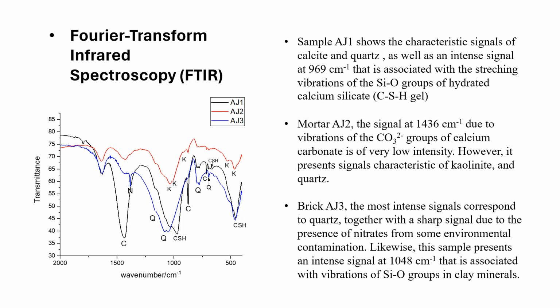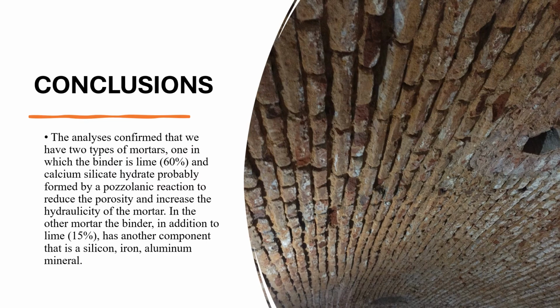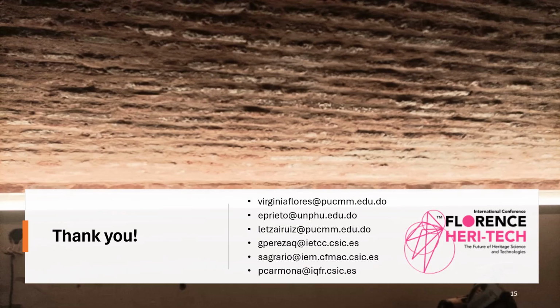We can conclude that the analysis confirmed that we have two types of mortars, one in which the binder is lime 60% and calcium silicate hydrate, probably formed by a pozzolanic reaction to reduce the porosity and increase the hydraulicity of the mortar. In the other mortar, the binder, in addition to lime, which is 15%, has another component that is a silicon, iron, aluminum mineral. Thank you very much.